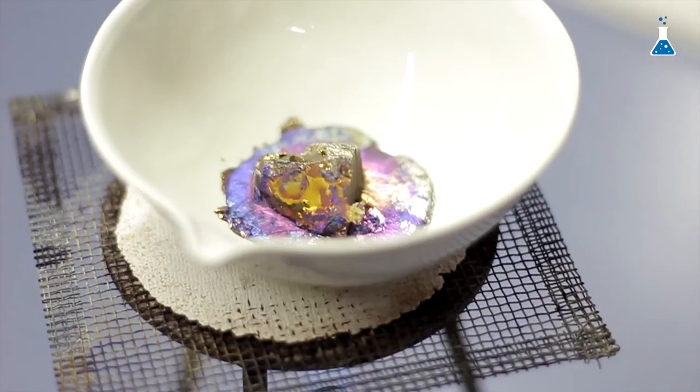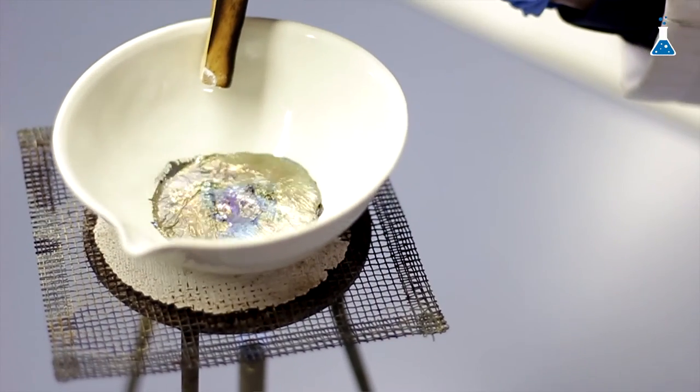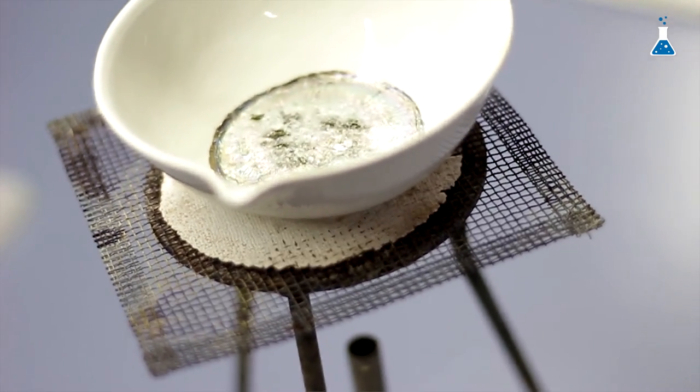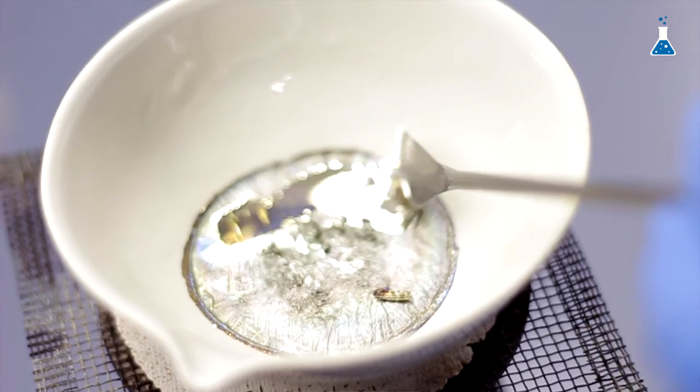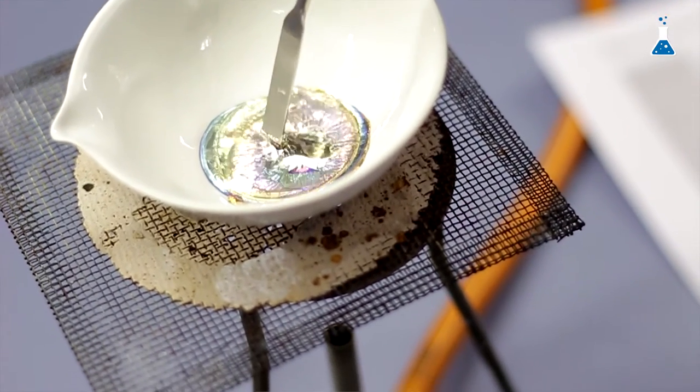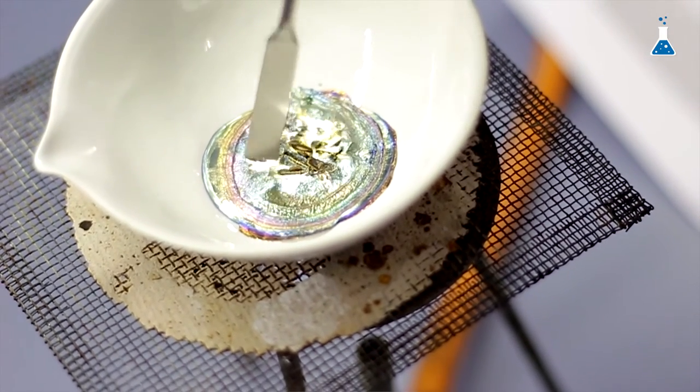As you can see, the metal slowly becomes liquid and when it is completely melted, we turn off the heat. There are some oxides and contaminants on the top which can be skimmed off with a spatula and we are going to pour away the molten metal to a new clean crucible which is recommendable to be preheated in order to avoid the crack from temperature shock. As the material is cooling down, we will observe how crystals begin to form at the bottom.